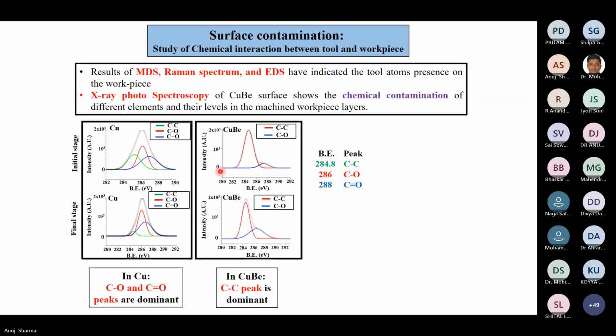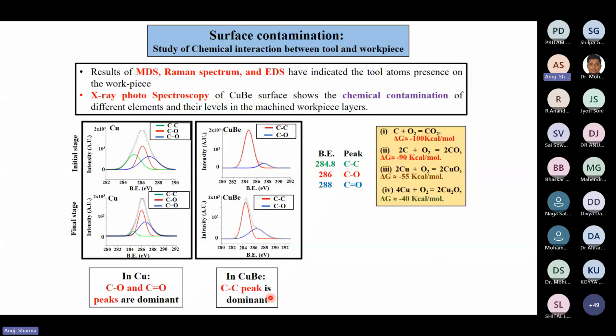In copper, mostly the C-O and C double bond O peaks were dominant, but in copper beryllium, the carbon peak is dominant. By comparing with Gibbs free energy, we can see which reaction is dominant. If we check all these chemical reactions, delta G is more negative in these 2 cases. So these 2 reactions are more dominant on the surface, whereas the others have higher energy, so they are not feasible reactions.